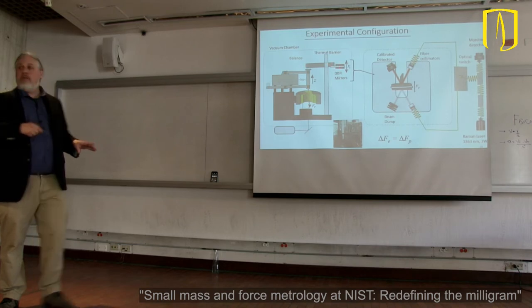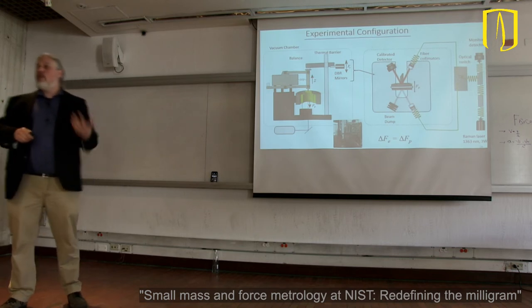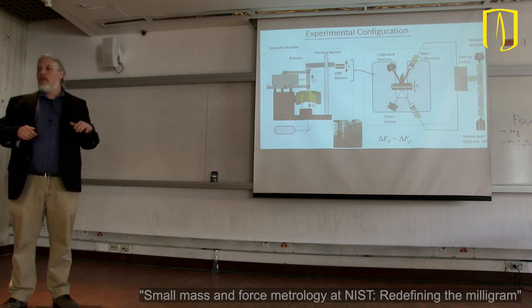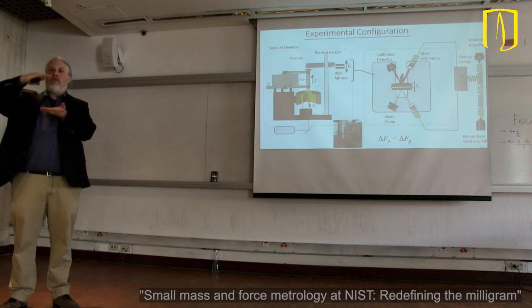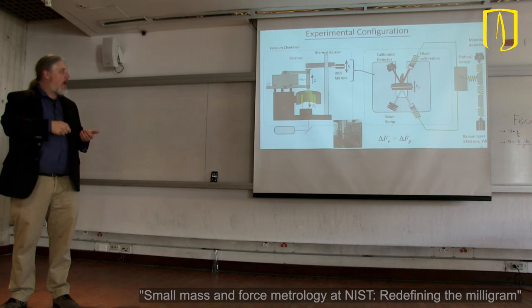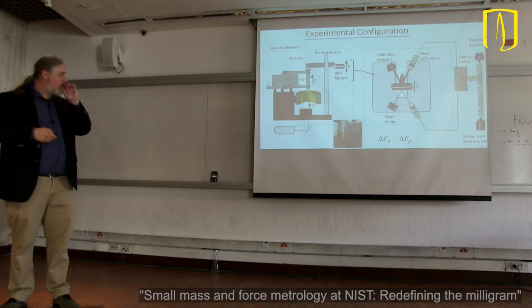And then on the other end, we put some very high reflectivity mirrors. These are actually grown at NIST. They're semiconductor mirrors, what are called distributed Bragg reflector mirrors. These are layers of semiconductors grown to produce a very, very high reflectivity, about five nines reflectivity.